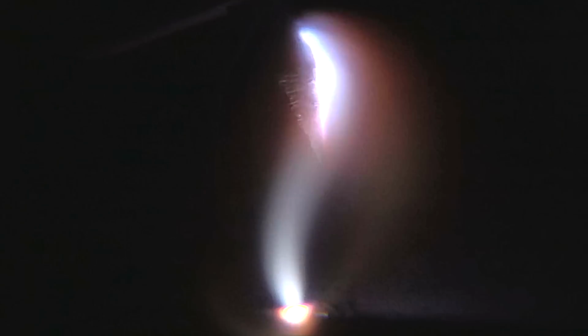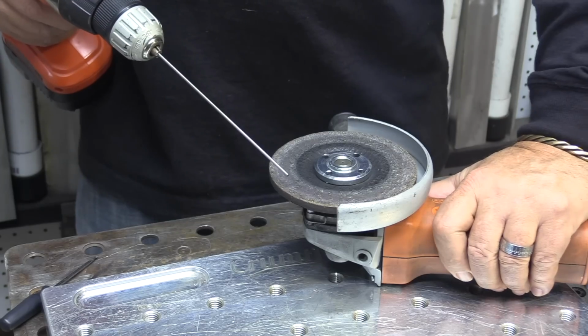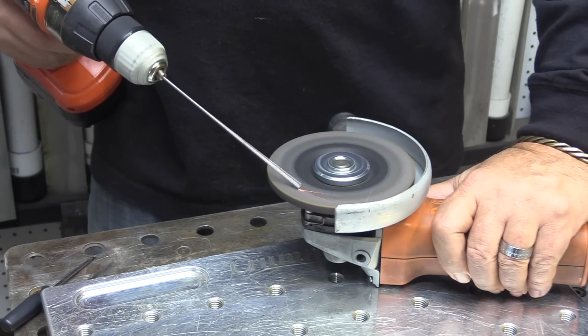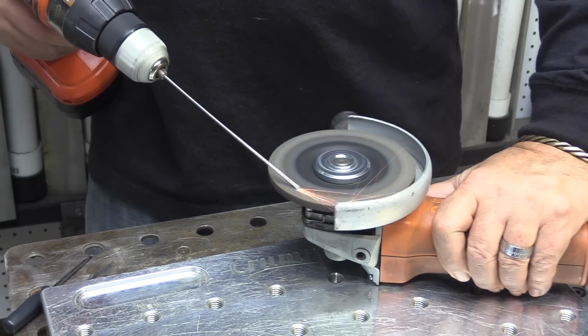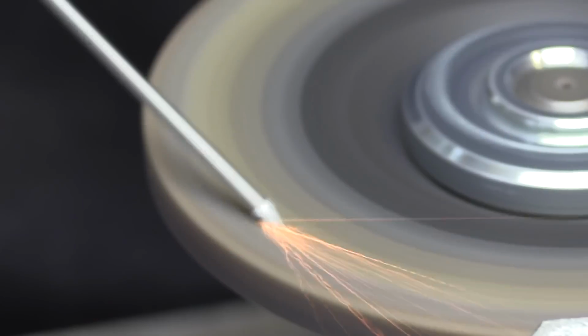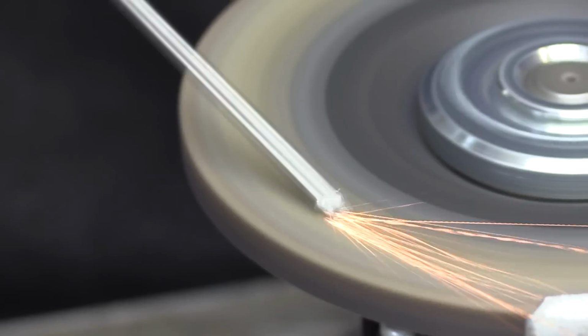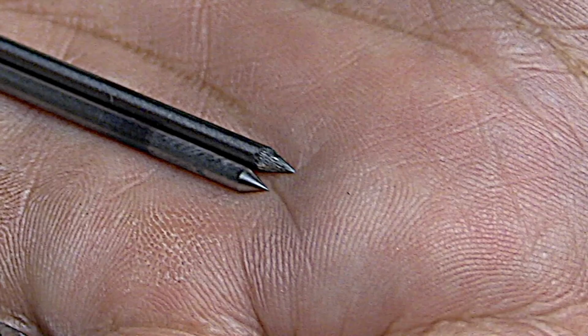This is that in slow motion. This won't happen every time, and I've got it magnified here so it looks like it's a longer arc, but it's just blown up a little bit and in slow motion. Now that won't happen every time, but it happens when you least want it to happen, like when you're right next to some thin cooling fin. The way to cure that if you don't have a tungsten grinder is get those scratches running lengthwise like this. Even rough grinding marks will do better if they're running lengthwise.